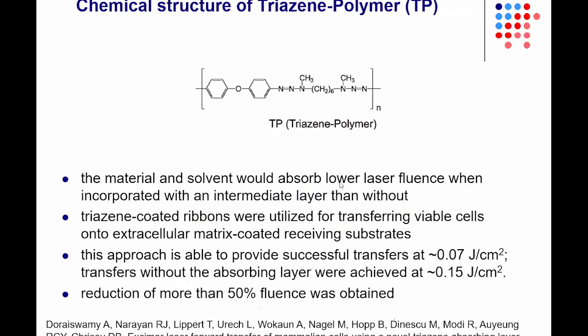One thing that we've done is to try to use polymers to reduce the amount of energy imparted to the cells during the transfer process. It's being done with a triazene coated ribbon. So this triazene polymer essentially is able to have a reaction that absorbs laser fluence, and by having this as an intermediary layer, it essentially protects the cells from directly interacting with the laser energy. And so by having this triazene coated ribbon, you can reduce the energy needed for laser transfer down to 0.07 joules per centimeter squared versus energy of 0.15 joules per centimeter squared that would be required otherwise.